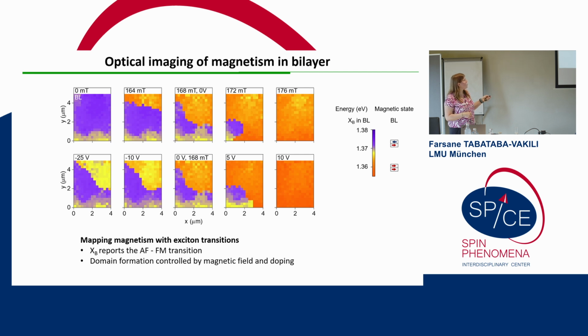And so we're just going along the sample step by step with our nanopositioners and measuring a DR spectrum in every position, and then just tracking the exciton energy here for XB. As we apply a magnetic field along the in-plane B-axis, we observe the nucleation of a ferromagnetic domain here at the edge of this bilayer region. Then as we increase the magnetic field, this domain expands and continues to grow until it ultimately encompasses this entire region. And the corner here on the bottom left that flips last is close to the monolayer.